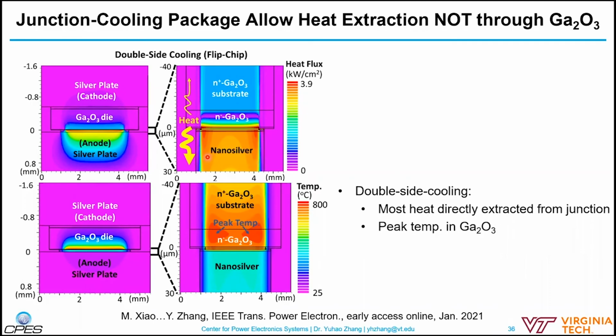I mean, this is the sintering, because in the sintering there are also many interfaces. So the thermal resistance is not that low. Essentially, if this gallium oxide substrate can be changed to diamond or silicon carbide, then from our simulation, to predict the heat extraction upwards, that path will have an effective thermal resistance similar to the bottom. So the heat can be extracted from both the upwards path and the bottom path.